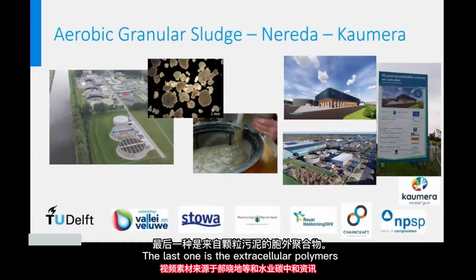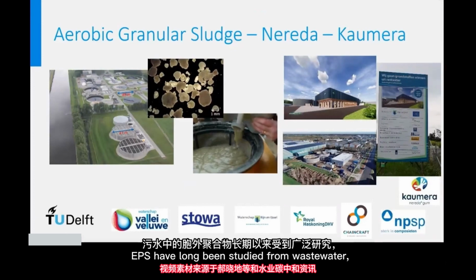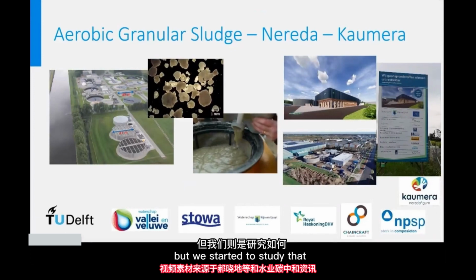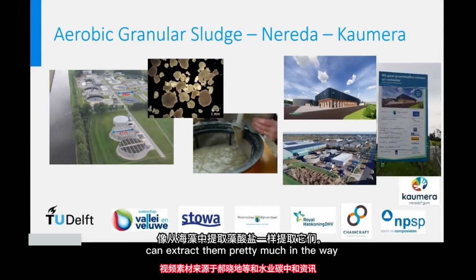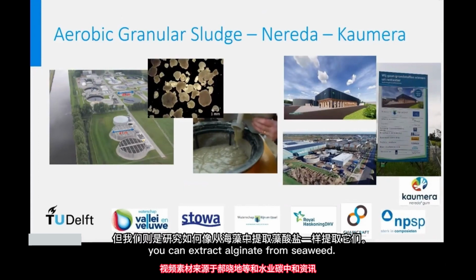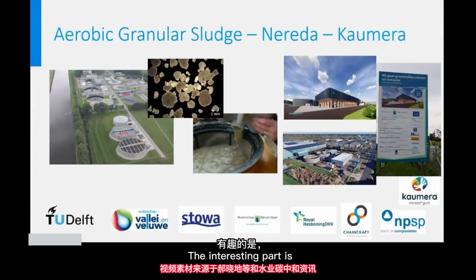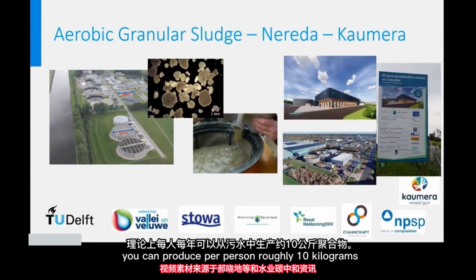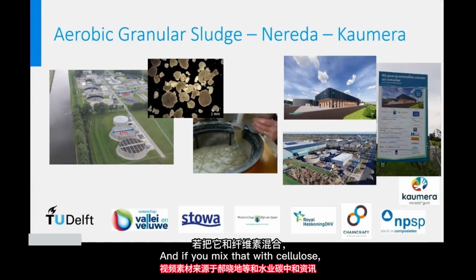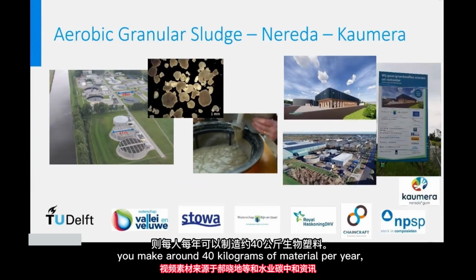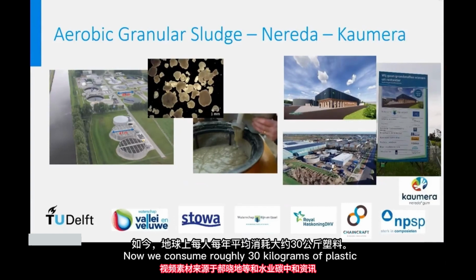The last one is the extracellular polymers from granular sludge. Extracellular polymers have long not been studied from wastewater, but we started to study that. You can extract them pretty much in the way you can extract alginate from seaweed. The interesting part is you can produce per person roughly 10 kilograms of this polymer per year from the wastewater. And if you mix that with cellulose, you make around 40 kilograms of material per year, which is a plastic-like material. Now we consume roughly 30 kilograms of plastic per year, average on Earth.